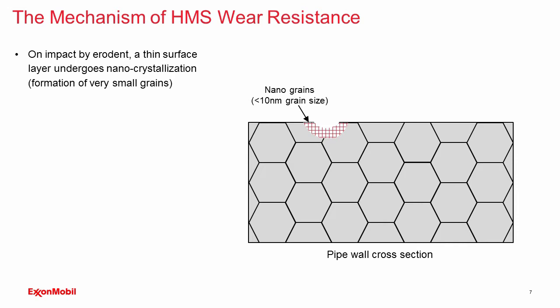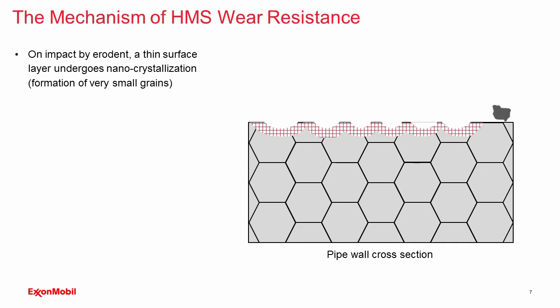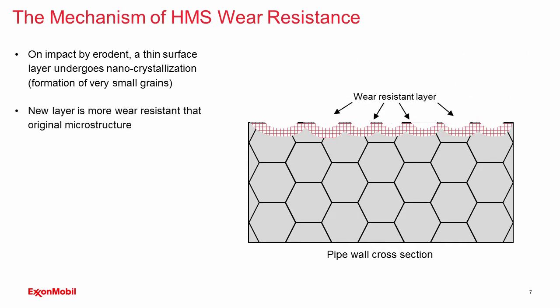The average grain size is about 10 nanometers, and so you can imagine the continual process here inside the slurry pipeline as the material wears away. Yes, material is physically removed, but at least there's a thin layer underneath the surface that transforms to very fine grain and has better wear resistance. In this regard, you can refer to this material as a smart material because it's having a positive reaction to the service environment. We've done a lot of microscopy.